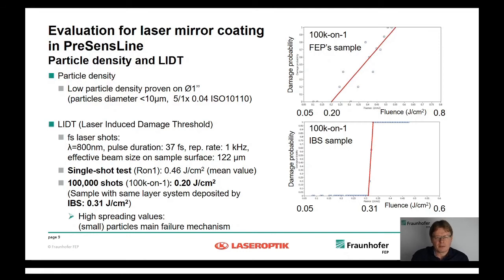LIDT measurement was done by a partner. They used a femtosecond laser with a very short pulse duration, only 37 femtoseconds. This LIDT measurement with a femtosecond laser usually has quite a high impact on the samples, on the laser mirrors, and usually leads to quite low numbers in comparison to picosecond lasers, for example. So the numbers are low anyway using this short pulse duration. For the single shot test, we got 0.46 joule per square centimeter, which is a quite good number. For the 100,000 shots at one spot, we got 0.2 joule per square centimeter.